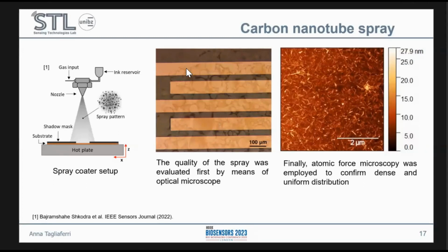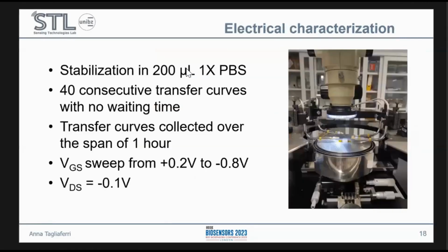At this point, we had to go on with the electrical characterization. We did this by using a semiconductor device parameter analyzer, or probe station. And we performed the test using 200 microliters of 1x PBS. We had a mixture of salts and minerals dissolved in the solution. We measured 40 consecutive transfer curves or IV curves with no waiting time in between each other. This means that the transfer curves were collected over the span of 1 hour.